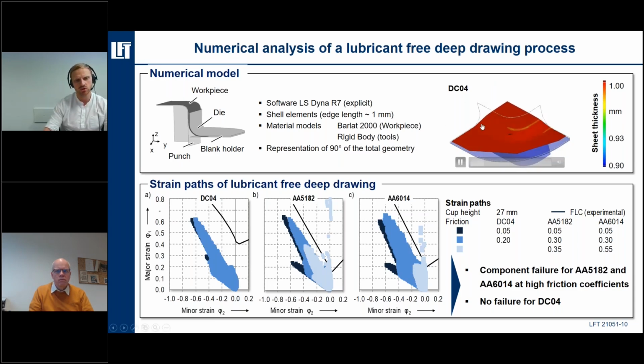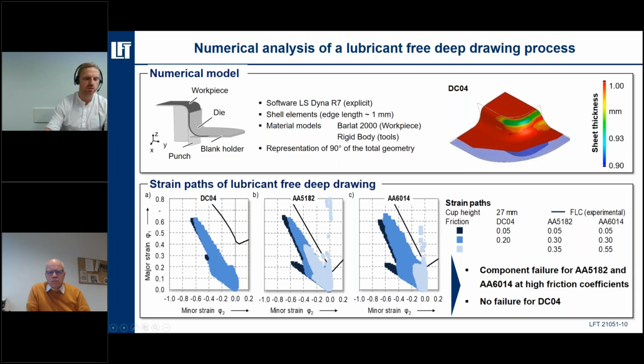The rectangular cup, which can be seen in this upper right corner, has a cup width of around about 50 millimeters and a length of about 90 millimeters. To reduce the computational time, it's normal that the symmetry of the workpiece is used because in all missing parts, the same results are expected. For these FE models, different materials have been used. In this regard, DC04 steel material, as well as two aluminum alloys, AA5182 and AA6014, have been used with a sheet thickness of 1 millimeter as workpiece material.